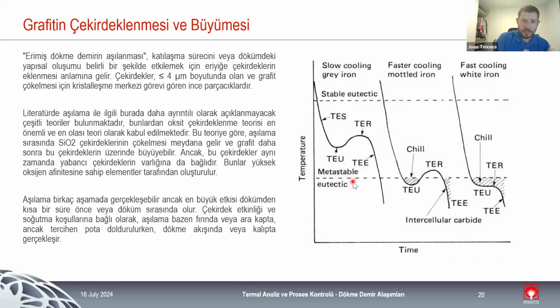So with this, we can understand that we need to play with two different things for us to have a good inoculation step. We need to have inoculants, ferrosilicon with some active element to promote the formation of stable solidification of graphite. And we need to also be careful with the carbide promoters that we have in the base metal. The chromiums, the boron, vanadium, titanium, elements that we normally receive from the steel scrap or from ingot or from pig iron, we really need to be careful with the trace amounts of these elements to have a good inoculation step.